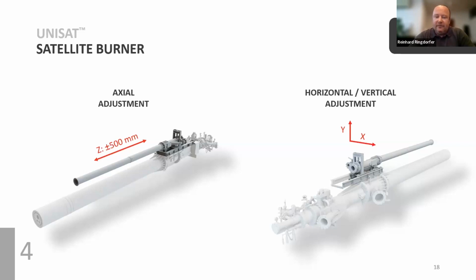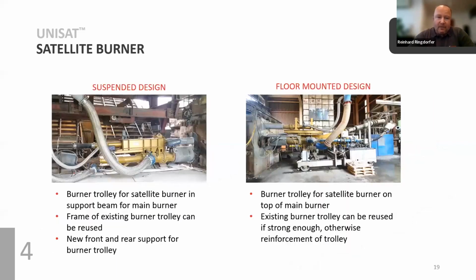This always depends. If the satellite burner is delivered with a new main burner, then it's easy because you put it on top. But if you install it at the existing location with an existing burner trolley, then you have to find the spot where you can put the satellite burner. With our satellite burner, it's possible to have both executions. So you have the suspended design burner trolley, where we can use either the frame, the support beam as burner trolley for the satellite burner, or it's a possibility to have supports, depending on the space availability below the main burner, so that we can have the satellite burner on top.